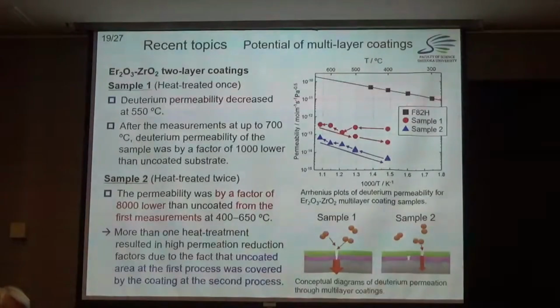Then when we think about different materials that can be coated, in this case, erbium oxide and zirconium oxide two-layer coatings give much better coating property than a single-layer coating. In the single-layer coating, sometimes it degrades after permeation measurement at high temperature, like 700 degrees C. However, the multi-layer coatings give much better property after high temperature measurement.